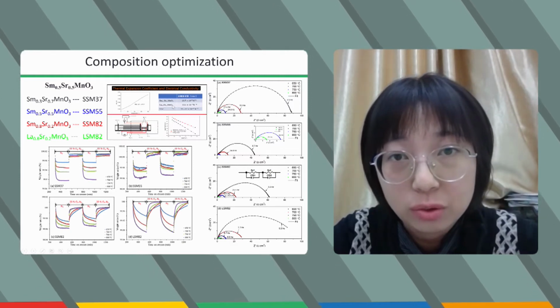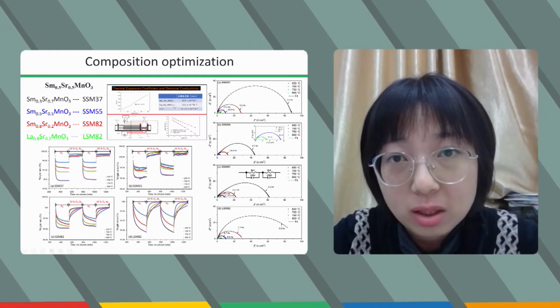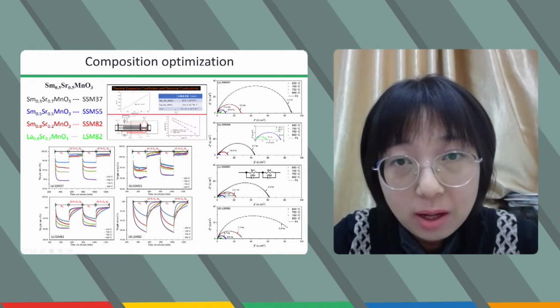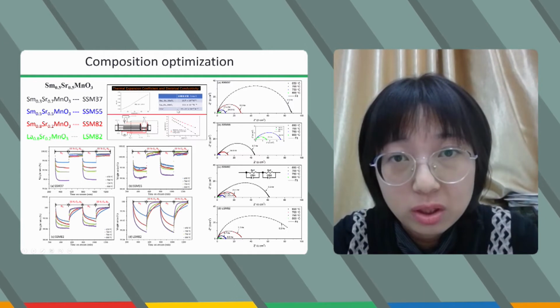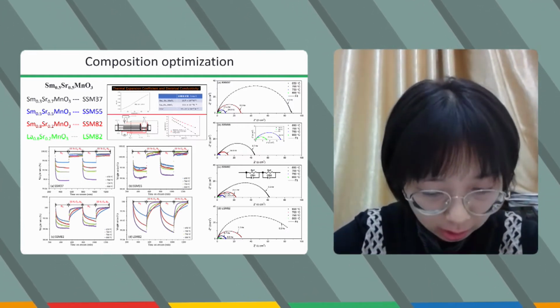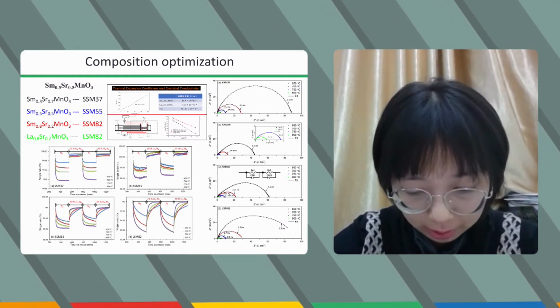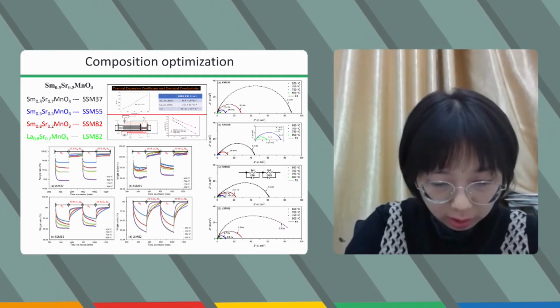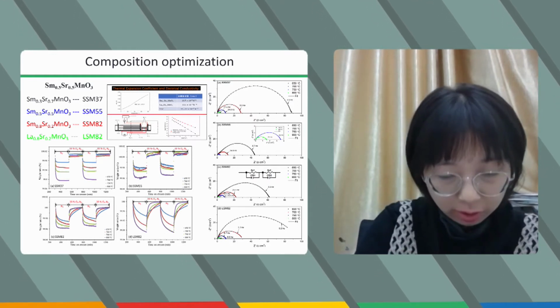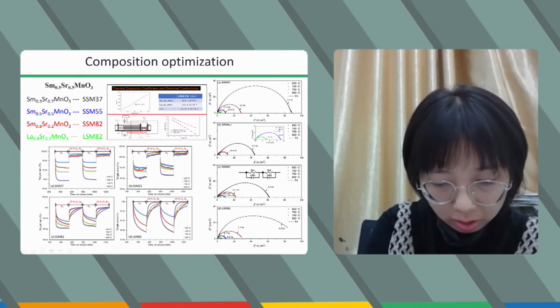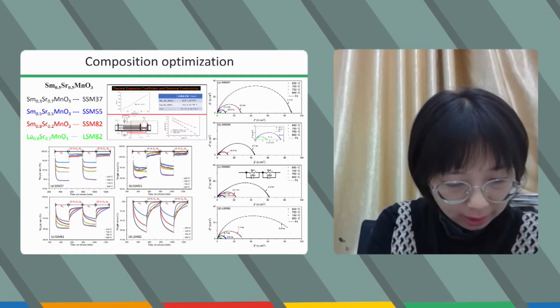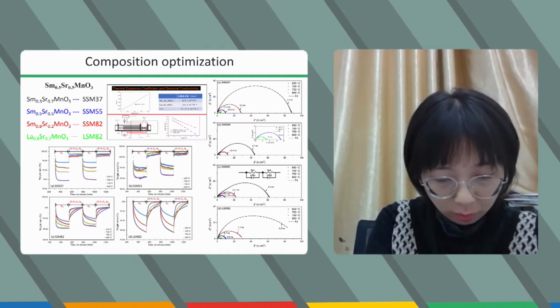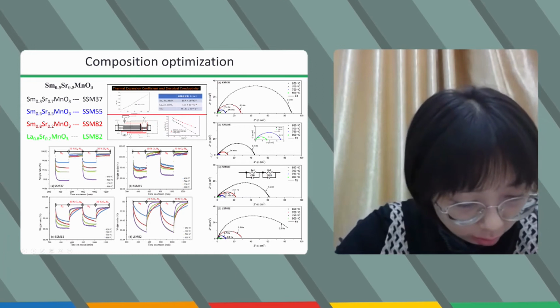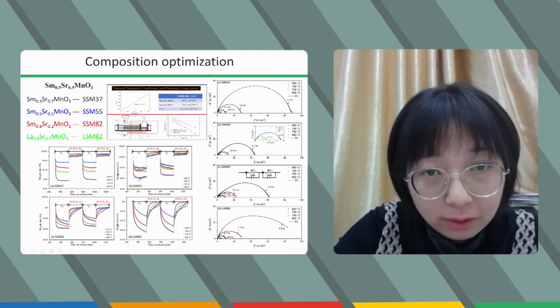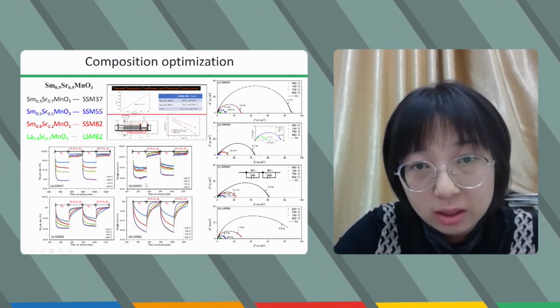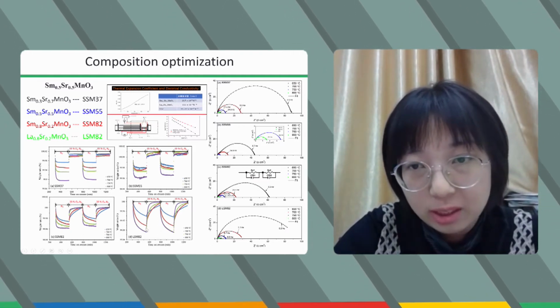We tested the TEC of the SSM and the traditional LSM, and we found that the TEC of SSM excels over LSM and is better matched with the traditional YSZ. The electrical conductivity of SSM is much higher than that of LSM. It has a closer TEC, and SSM performs better than LSM in catalyzing the ORR and in the uptake and release of oxygen effectively, where it takes a longer time for LSM. As you can see, for the first three, when we change the atmosphere, they uptake and release oxygen quickly, whereas LSM takes a longer time.